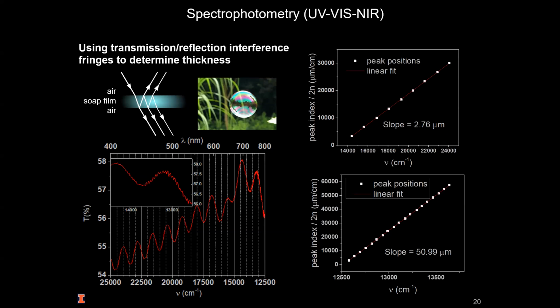Here, a sample composed of 2 layers of different thicknesses is analyzed. You see more high frequency signal here, on top of a low frequency signal, and those correspond to the 2 thicknesses of films. The periodicity of the fringes is constant with wave number, so plotting peak index against wave number, we get a straight line whose slope is proportional to the product between refraction index and thickness.